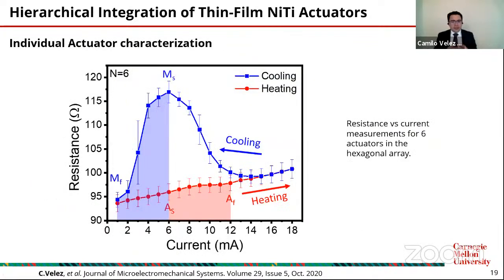One of the most important tests that we perform on these actuators, because at that scale it was very difficult to find the hysteresis curve: you can find the hysteresis curve on the thin film when you deposit it on the wafer, and you can measure the stress on the wafer. But once you release the actuators, you don't know if you are actually going through a phase change, or if you are taking advantage of the shape memory alloy at all.